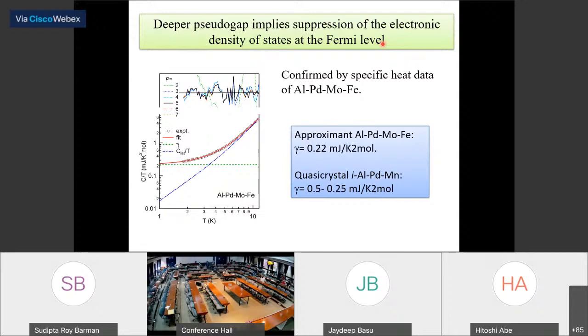The reason comes partially from the study of the core level, where we see that there is a stronger sp-d hybridization in the approximants, resulting from looking at the shapes of the plasmons. And we also look at the aluminium 2s line shape, their lifetimes, and we see that that might be one possible reason. So we observe a pseudo gap in high order approximants and it is deeper compared to the quasicrystal, which has a similar e/a ratio.